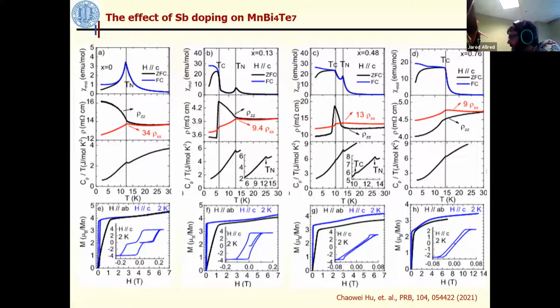I guess my deeper interest here was about how you characterize that environment. You mentioned neutrons gave you a refined occupancy. Was that just based on a crystallographic model? Yes, very good point. To characterize the antisites is actually pretty difficult. Difficult in the sense that they are van der Waals materials, and usually X-ray diffraction for van der Waals materials has some small bending, whatever.